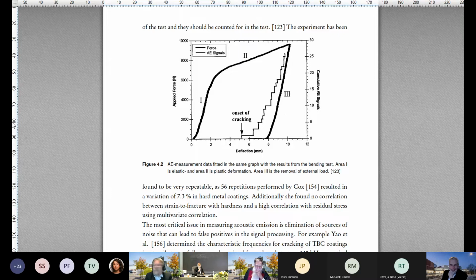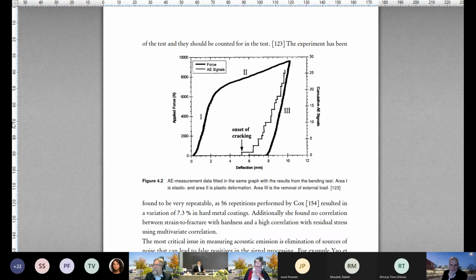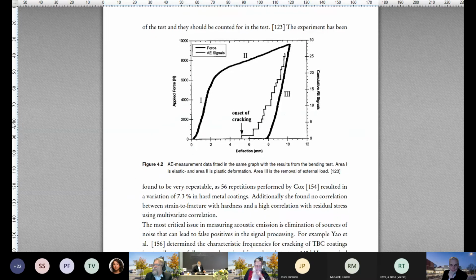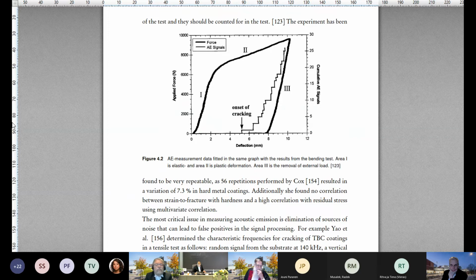Well, first of all, this 4.2, I didn't check right now, but it seems like it's not a ceramic coating since the cracking starts quite late. Okay. But thinking of a ceramic coating in compression, I'll draw again. So I would have this same coating, I'll make it a bit simpler. And you start compressing, which would essentially be the bending test in reverse. So you would have this ceramic here in compression.